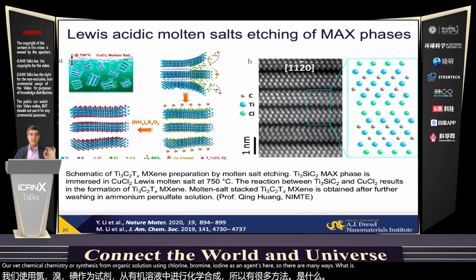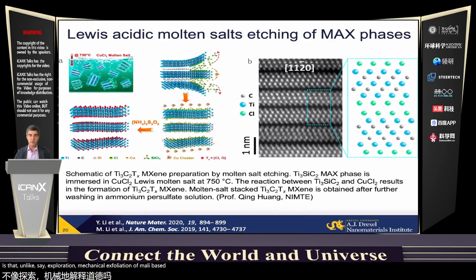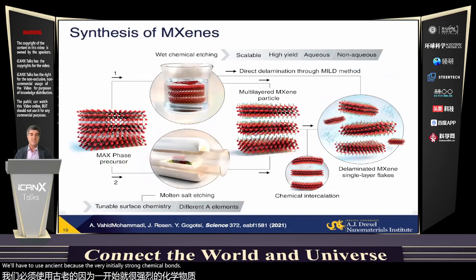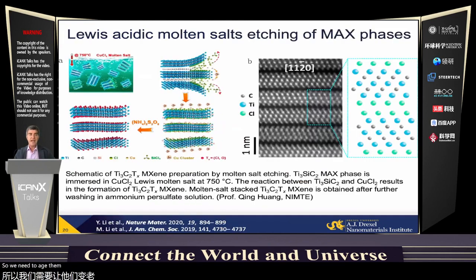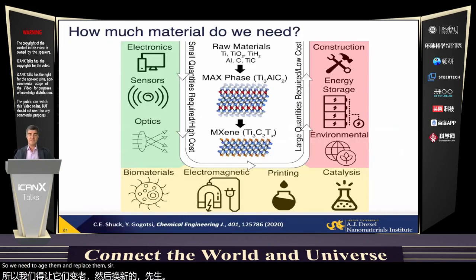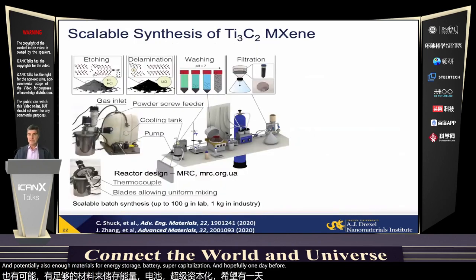What is important is that unlike, say, mechanical exfoliation of molybdenum sulfide or graphene, we have to use etching because there were initially strong chemical bonds between the A element layers and transition metal in the surface. So we need to etch them and replace them here. What is important in these things here? We can make not only small amounts of materials for electronics, optics, sensors, monolayers, but we can make large amounts of materials, making printable inks, catalysis, and potentially also enough materials for energy storage, battery, supercap application, and hopefully one day for even construction applications here.